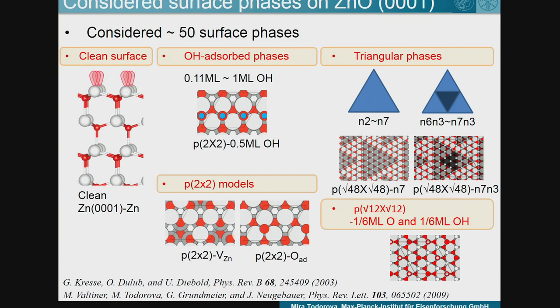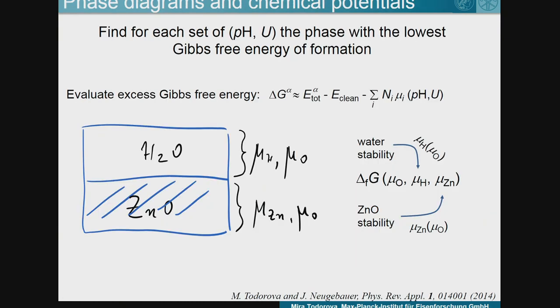Now, we've considered various surface models here: some OH groups in various coverages adsorbed on the cleaved surface. There are large reconstructions which have a triangular shape. Then we have a mixed surface termination. We do have vacancy or adsorbate structures. And we perform for each of these structures a calculation, DFT in vacuum, DFT with implicit solvent, and then use thermodynamic modeling, as indicated here, in order to evaluate the change in the Gibbs free energy.